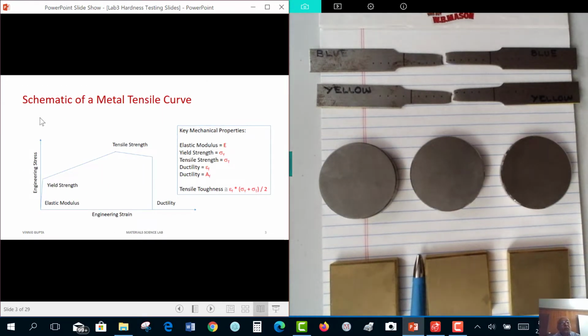So in lab number 2, we looked at tensile testing. And this is a schematic of a metal tensile curve. What we found is as we increase the stress, the material elastically deformed, elastic deformation only. And this portion of the curve was essentially linear, not necessarily perfectly linear, but it could be characterized by the slope, which was called elastic modulus. So this was our one major mechanical property of the material.